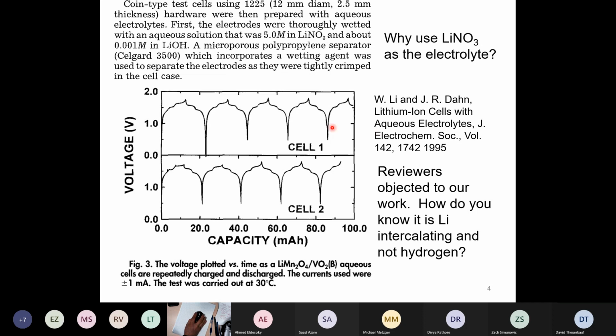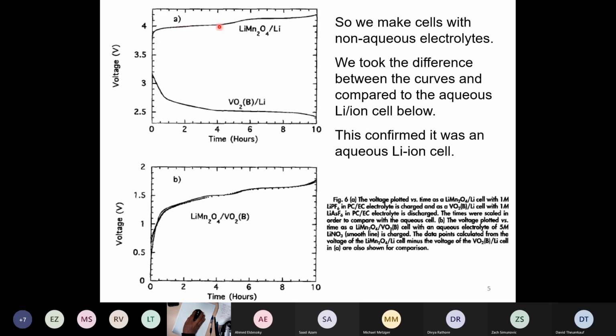Oh yeah, and the reviewers objected to this work. They said, how do you know it's lithium that's intercalating and not hydrogen? So this is what we did on the next slide. We made half cells with non-aqueous electrolytes, the typical lithium battery electrolytes. Then we took the 2 voltage curves from the half cells and took the difference between them, and compared that difference, which would be equivalent to a non-aqueous full cell, with the aqueous full cell. Down here it says the solid line is the aqueous cells, and the data points are calculated from these 2 half cells. This convinced the reviewers that we actually were operating with lithium ions going back and forth between the electrodes.